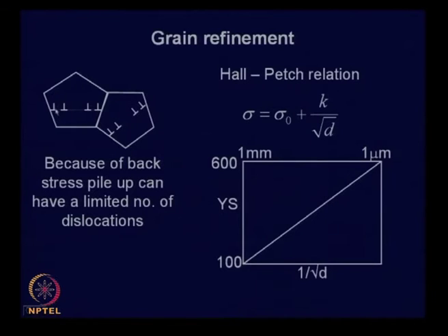And so, therefore, the grain size is an important factor. It determines how many dislocations it can accommodate, and if you recollect your earlier lecture, it has been shown that the strength of a polycrystalline material is inversely proportional to the square root of the grain size. D is the average grain size. And this is a diagrammatic plot: if you plot yield strength against 1 over root D, you will get a linear line, and from this you can find out sigma 0 and k.